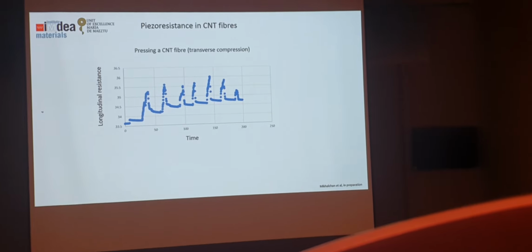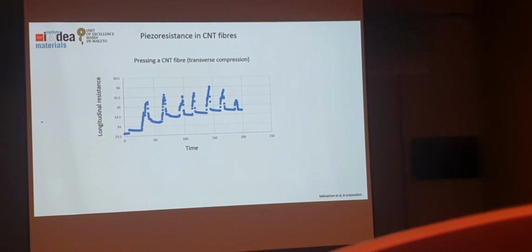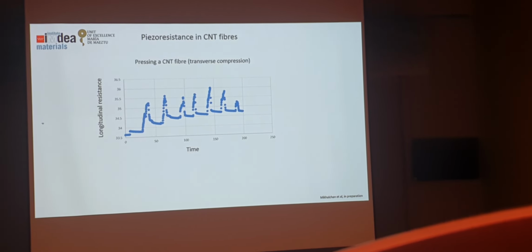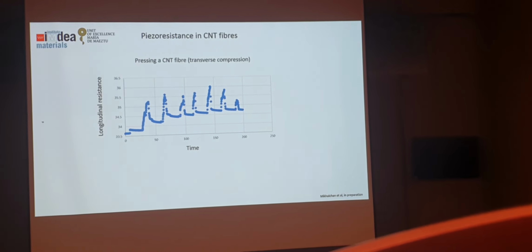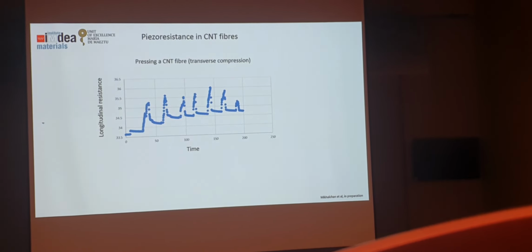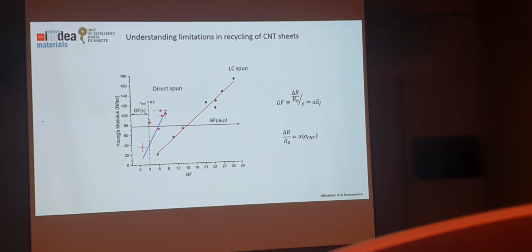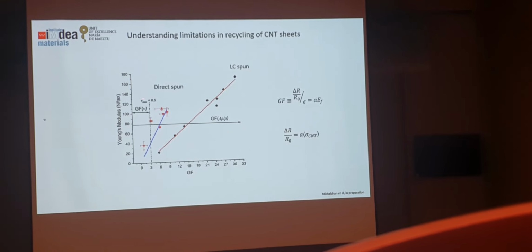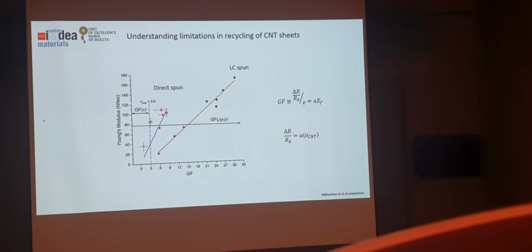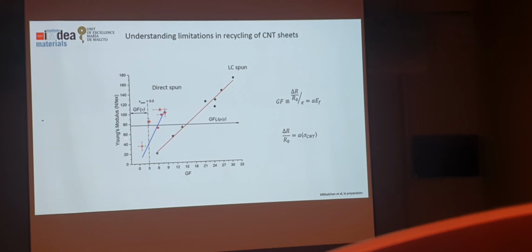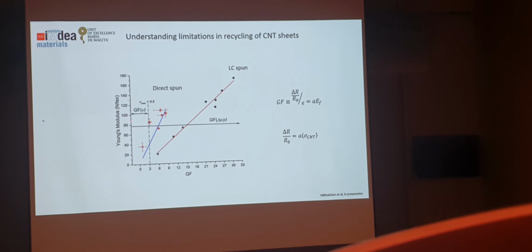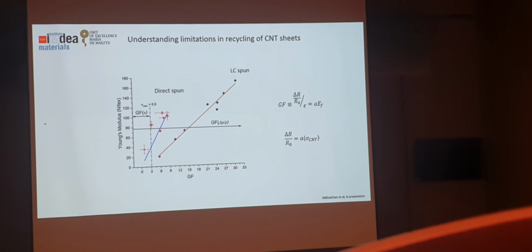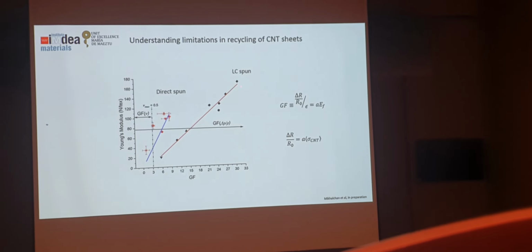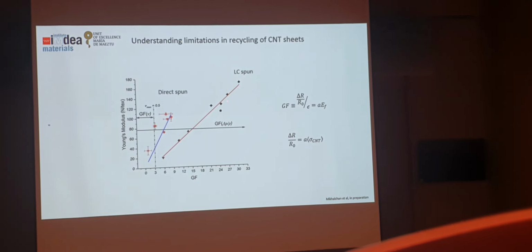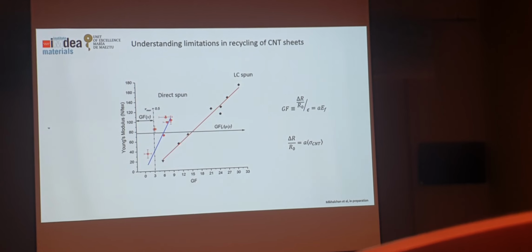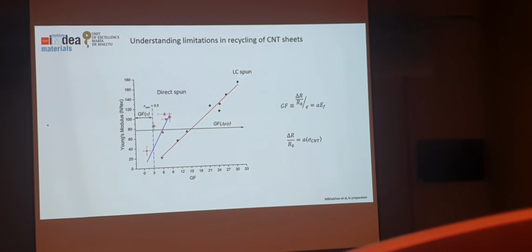So I thought, well, that's strange because nanotubes cannot be sliding, and the classical models you have for networks would not explain this. So we went and played with some of the floating catalyst material, and we found that, first of all, the gauge factor increases more or less linearly with modulus. We then got some material from Rice, which is much more uniform, and indeed, perfectly linear behavior. So, in other words, the stiffer the material, the higher the gauge factor.